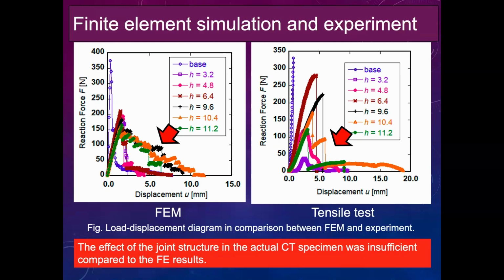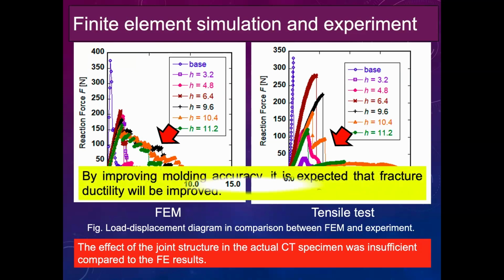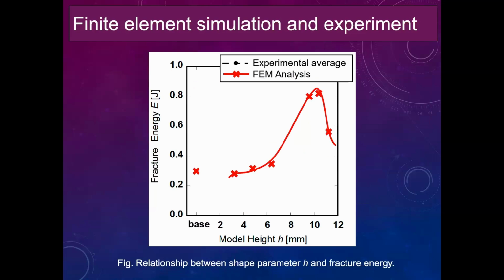Actually, the female part and the male part were molded separately and assembled before the tensile test to set up the CT specimen. So from this comparison, by improving the molding accuracy of the sickle joint in the CT specimen, it is expected that the fracture ductility will be further improved. So from this experimental data, this is the final data.